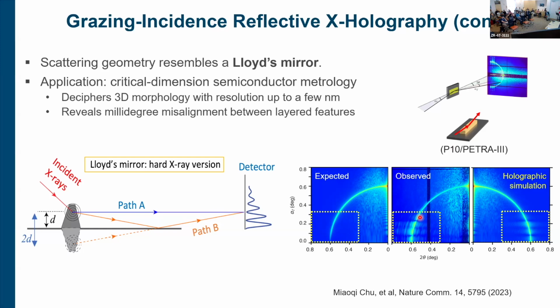We also have a simple calculation using the holography method, and this calculation matches the experimental data pretty well. But this is nothing else than a multi-beam effect. You probably know that. Some people call it a dynamic effect, but it's basically a multi-beam effect. If you don't assume a virtual source, actually a virtual, inverted object, you won't be able to simulate the experimental results. And if you use a conventional kinematic approximation with no multi-beam effect, that's what you get.